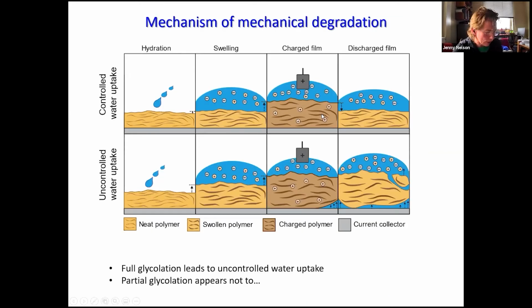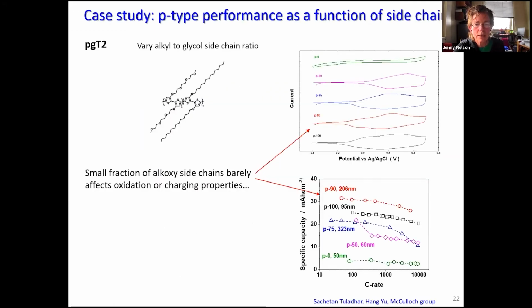So this is our kind of cartoon of what we think is going on, that when you have a polymer whose structure allows uncontrolled water uptake, that then leads to a kind of mechanical degradation of the polymer film during repeated cycling, and we eventually lose the polymer and it begins to break up and can no longer charge fully. That doesn't yet tell us anything about a microscopic mechanism. And to dig deeper into the mechanism, I'll just say a couple of words about work that we started.